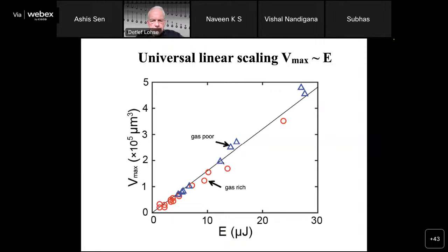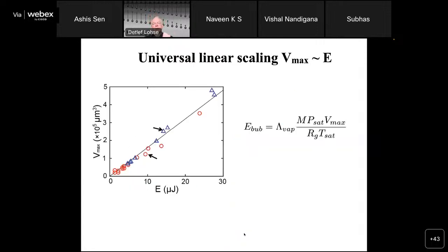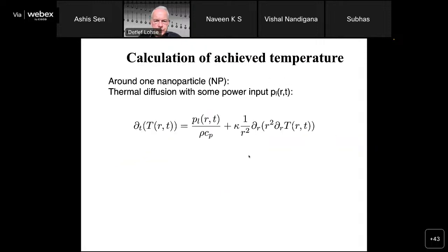This is exactly what you expect. Whether it's gas poor or gas rich doesn't matter. You have this linear relation between the volume of the bubble and the energy, and the delay time is really very, very crucial. And we can even calculate the slope of this relation. What we now do is calculate the achieved temperature. So this is simply diffusion.